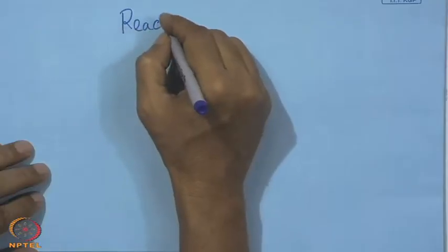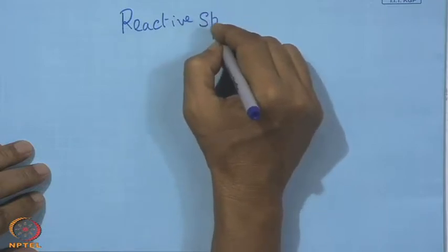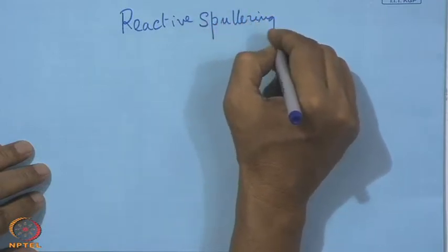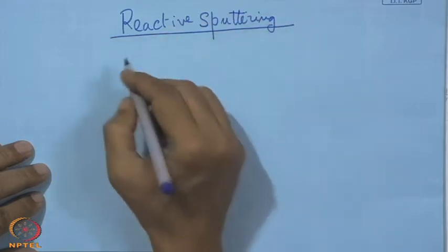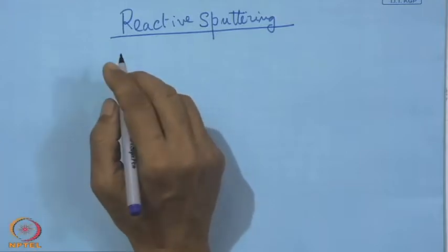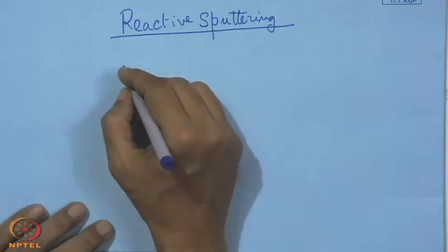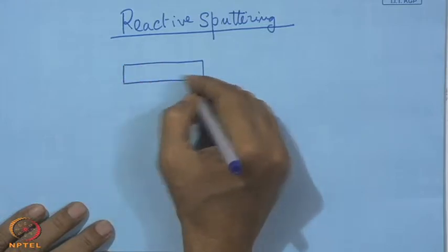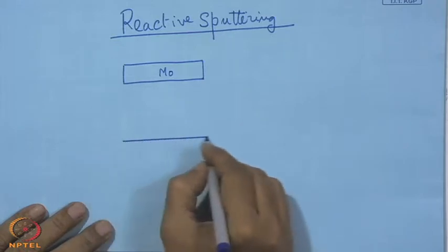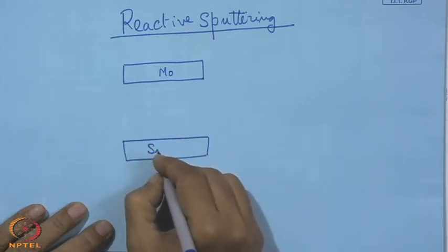So, this is one thing one has to look at, but apart from this, it is also possible, instead of using a target which is made of MoS2, what we can also do is called reactive sputtering. In that case we have one molybdenum target and then we have one substrate facing this molybdenum target.